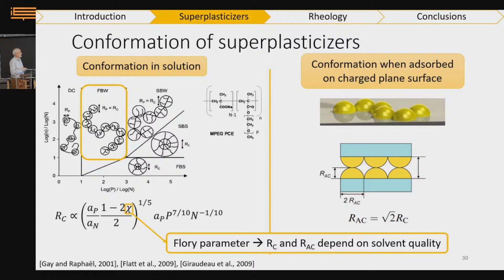So in solution, you have blobs. If adsorbed on the surface, Robert Flatt has shown experimentally doing AFM that the blob model remains correct. You just have an excluded volume due to the presence of the surface, but it doesn't basically change the thermodynamics. You just have a square root of 2 prefactor here, if you want to describe the radius of the blobs adsorbed on the surface with respect to the blobs free in solution. They scale in the same manner.